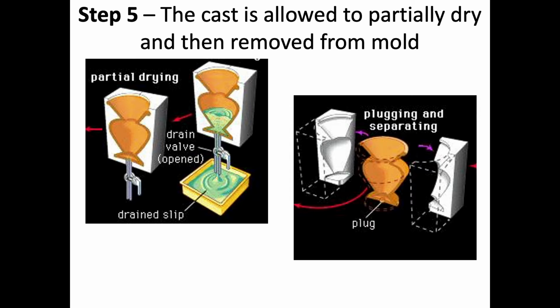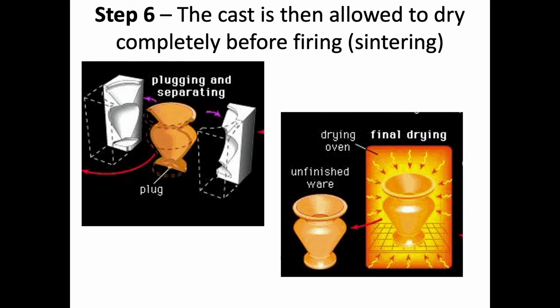Okay, so at that point, the cast is typically allowed to partially dry. So after we've gotten rid of all the slip, we typically let that green ceramic dry in the mold so that we can remove it more easily. And so typically these things are built so that you can take them apart and remove the shape from within. And then after it's taken out of the mold, you typically let it dry even further to get rid of all of the liquid. And then at that point, you can sinter the part.